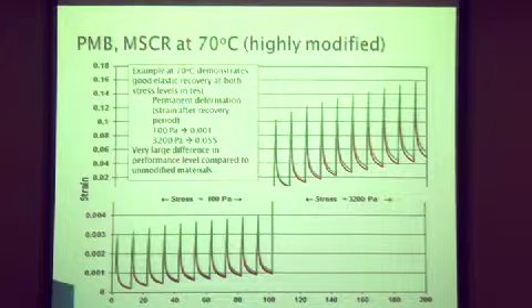What was the number I had before? 200, yeah? What's my number now? 0.05 maybe? It's virtually nothing. If I had that on the same scale, that would all be crammed down right at the bottom. So really here I've got something which is behaving very close to a viscoelastic solid. Same binder, same PG 64-22 binder, but I'm using a lot of polymer with it. So this is showing what you can do with modification. It also shows how that test can distinguish very nicely between the polymer modified binders and the conventional binder.